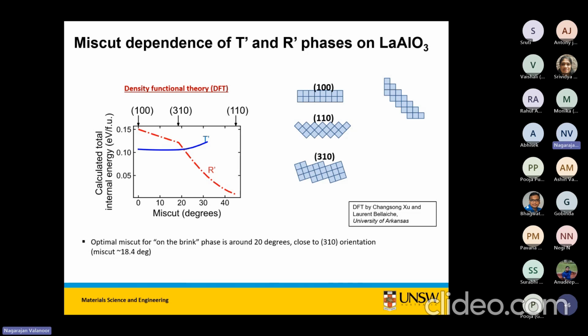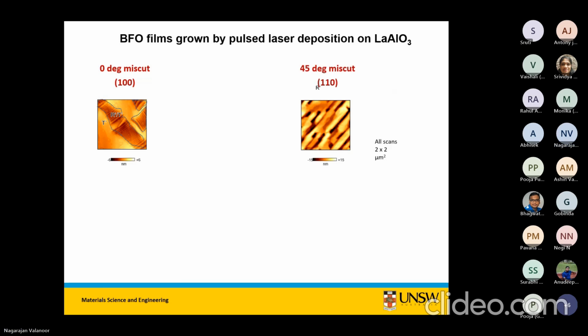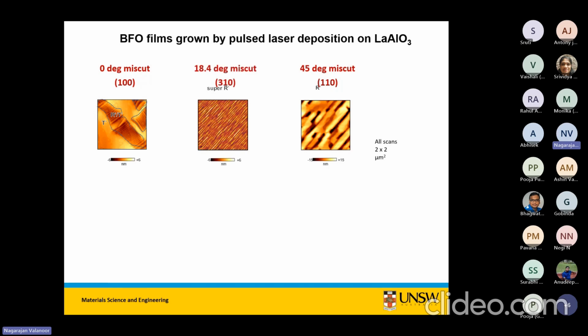So what we found is that 18.4 degrees, which is close to the 310, is excellent for pushing that polarization to the brink, which means anything more, it will say, to hell with you, I'm just going to relax myself with ferroelastic domains and go back to my bulk state. Right? So we're on the brink, which is great because that's exactly where you want to be when you want a large piezo response or any large susceptibility response. So how does it look if you grow it on 100? As I said, on lanthanum aluminate, you get the standard mixed phase. If you've done 110 growth, you get the stripy phase. But you grow it on 310, you get something that is somewhere in between.